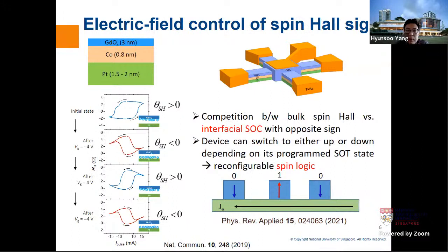A similar issue will happen in our case too. But the interesting thing is we are not using very large current penetration into this oxide. What we are doing is just applying the voltage on top, and then sending ions, oxygen ions. We are not really penetrating high-potential electrons into this oxide. So my speculation is our device stability will probably be much better than flash memory. Thank you. I think we have time for one more question, maybe.